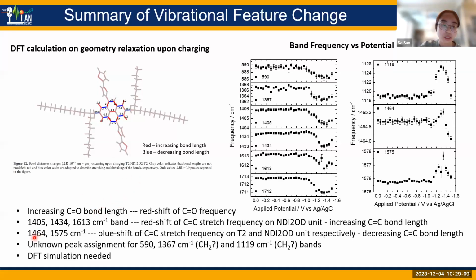If we use similar logic, we can see that these four bands also have redshift. Those are the CC stretch on the NDI2OD unit. They all show redshift, which may indicate increasing CC bond length. And these two peaks showing blue shift may indicate the CC stretch on the T2 and NDI2OD unit with a decreasing CC bond length. From the literature, I actually haven't found the peak assignment for these three peaks. So I think a more rigorous DFT simulation on the frequency shift or the bond length change upon chemical or electrical doping will be needed. It would be very helpful.